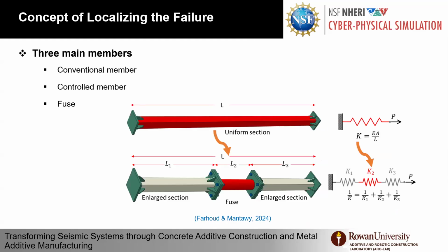So what we thought about this is, instead of having a very long bulky element here, which is the brace that we need to repair or replace, or eventually replace the building because of the damage, because we cannot repair the building, could we actually segment this into 3 zones or 2 zones where we enlarge the outer element, as you can see, so we keep them in capacity protection, so no yielding, no buckling, while we concentrate or localize the damage only on those fuses in red color.